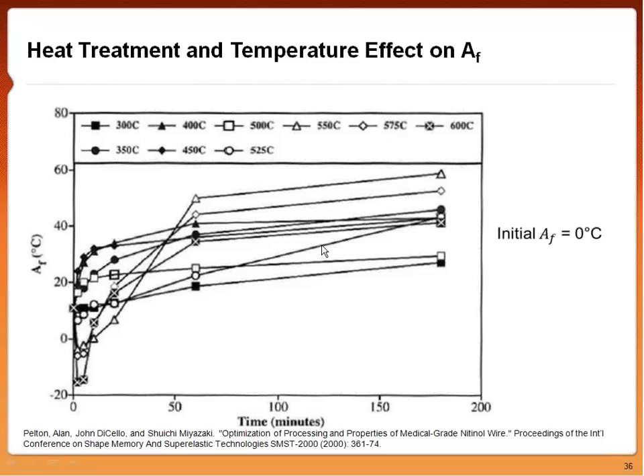If you want something where you slightly drop your AF, but you want to keep good material properties, you might pick something that's just slightly over 500 degrees Celsius, such as 525 in the blue circles over here. You see, we start here. We initially drop, and then we reach a point where we plateau. So again, this is just things you need to keep in mind when you shape set and when you play around with heat treatment times and temperatures for your nitinol material.